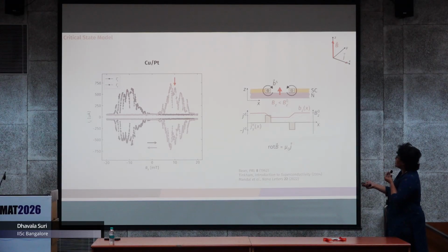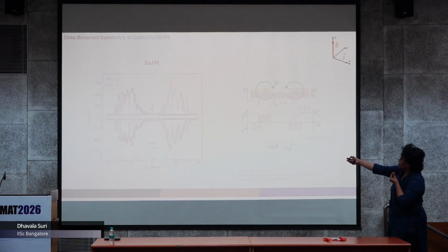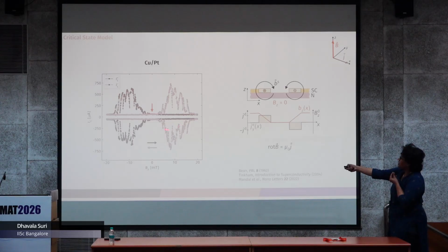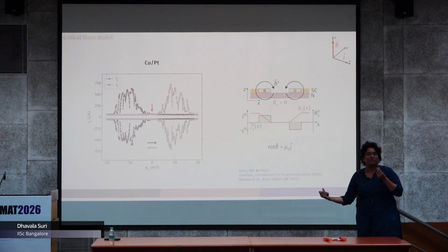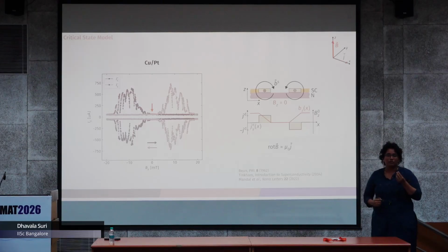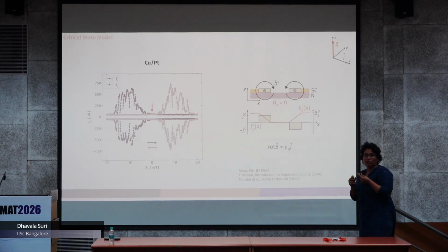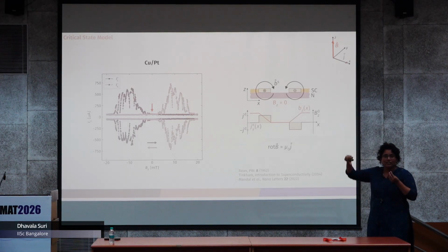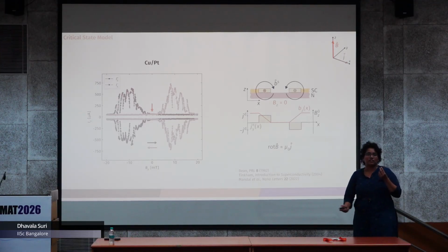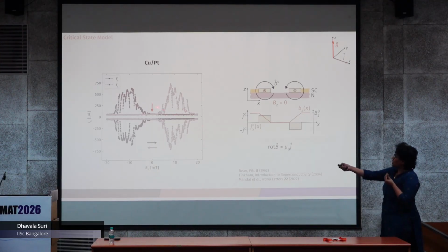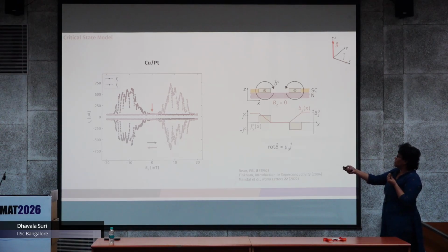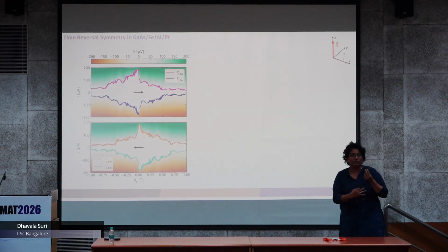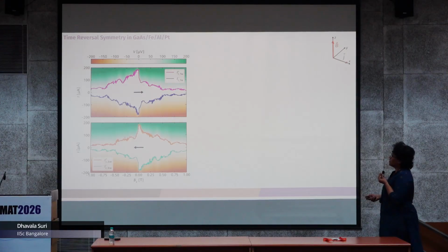And what happens is you keep on doing this process, and then if you come here, you see that you're sitting at zero magnetic field technically in the superconducting magnet that you have, but you actually have trapped vortices which have exactly negative field of some magnitude. So overall field seen is zero, and that can give rise to a maxima in the Fraunhofer interference before you cross zero. Okay, so that is one thing.